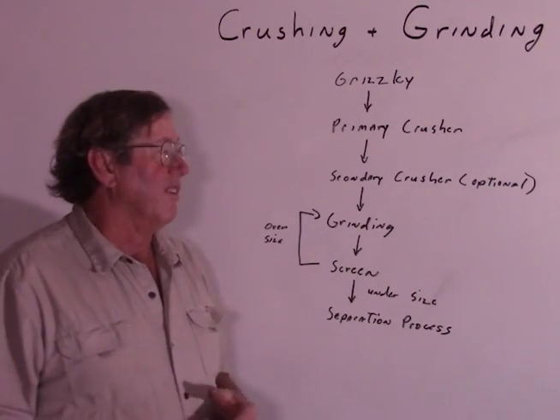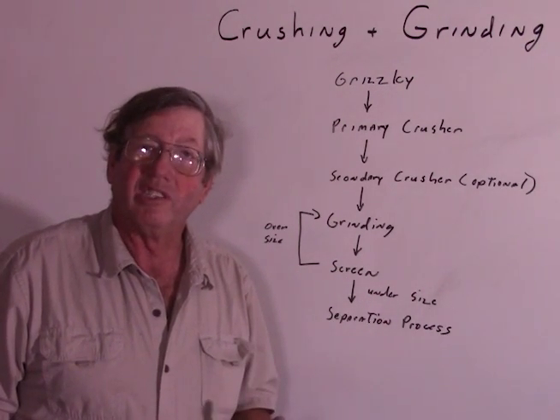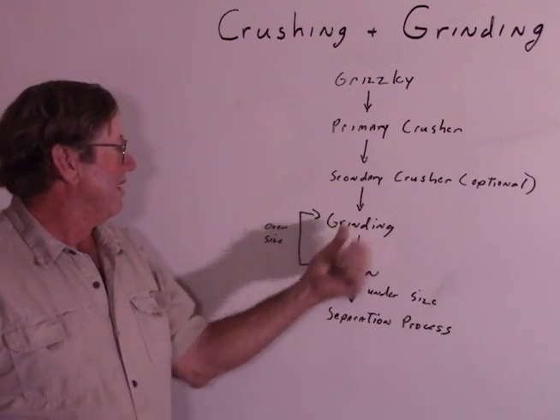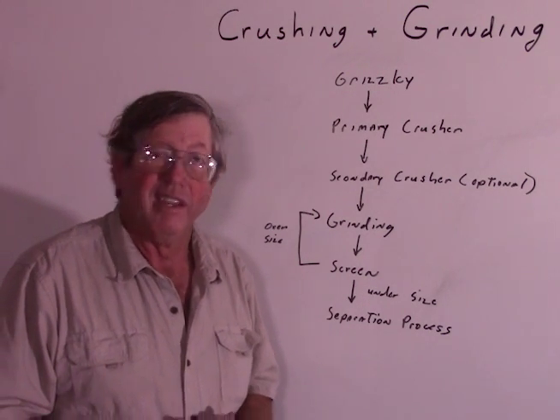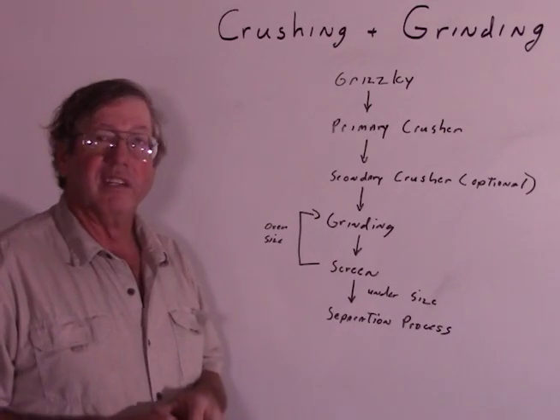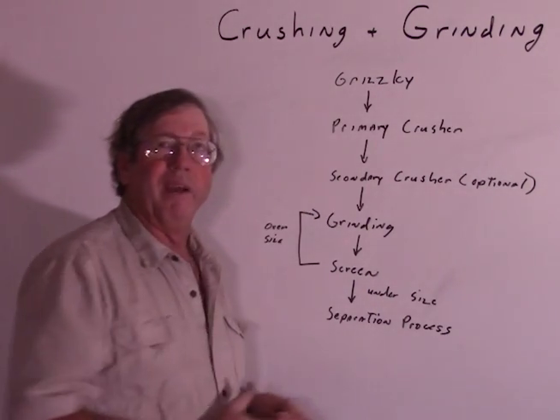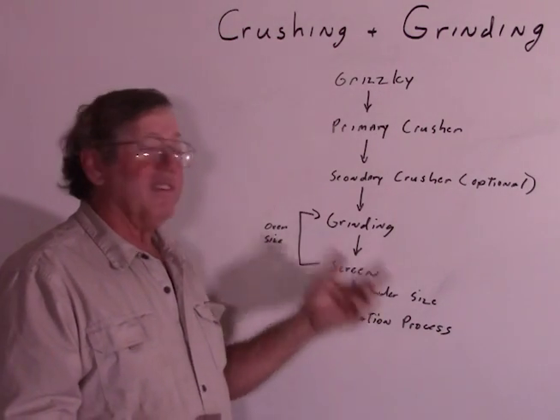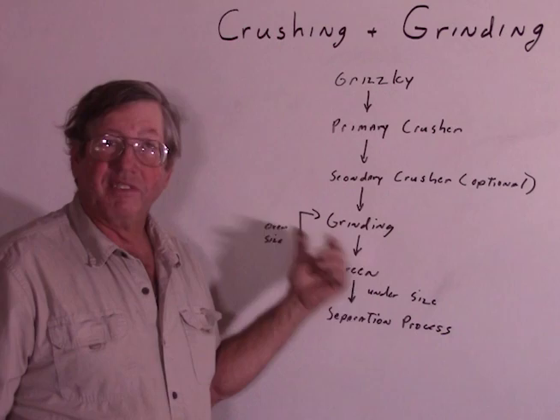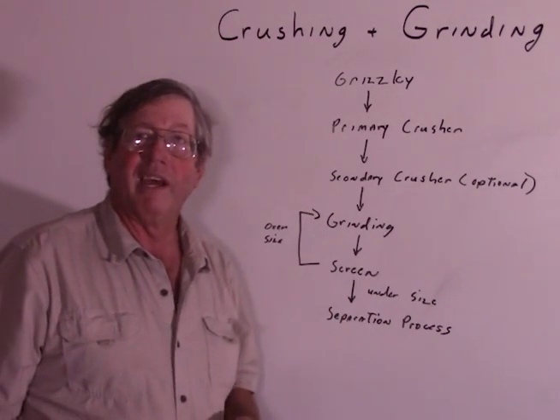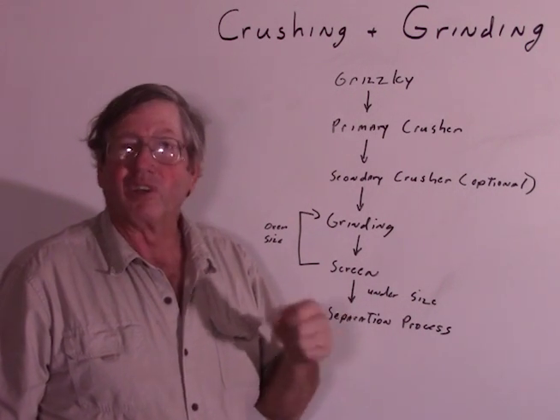The stuff that's rejected by the screen is called the oversize. In many processes you have recirculation in your grinding — any oversize will get recirculated in the previous phase for regrinding. To get say 95% passing 100 mesh in a single pass, you're going to be grinding very thoroughly and using a lot of energy and wear and creating a lot of fines, potentially unnecessarily. If a single quick pass gives you 80% minus, just screen it and send the other 20% back. Things will go a lot faster — you'll increase your throughput and decrease your overgrind.